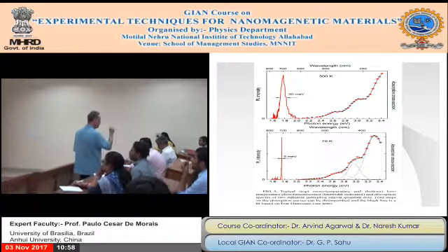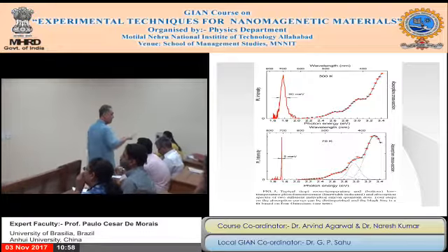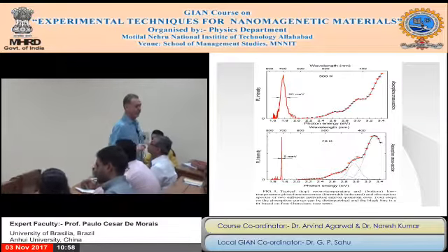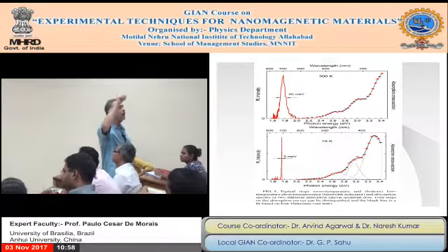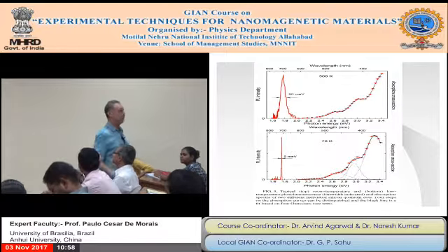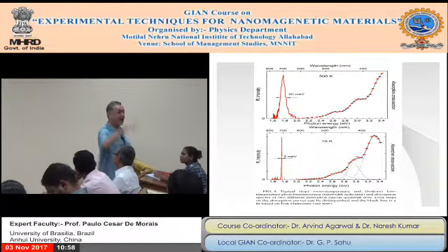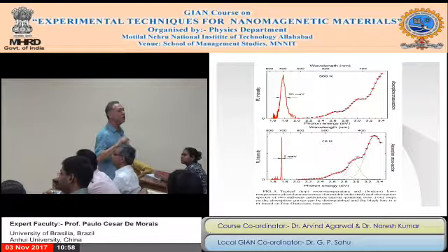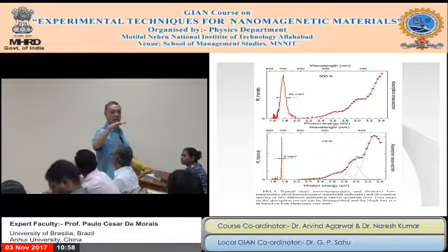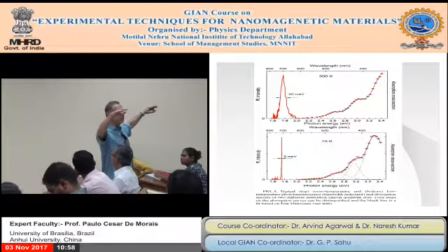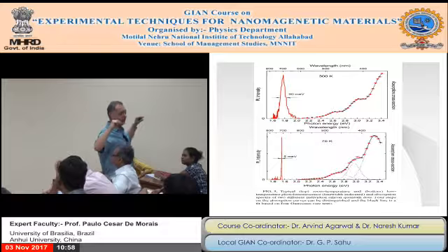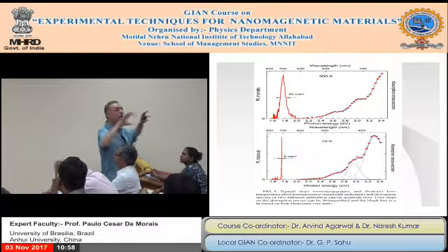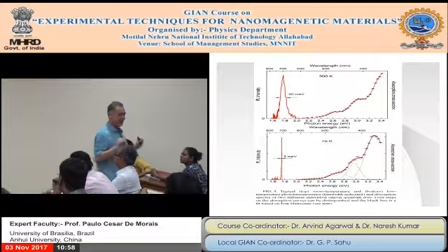The best way is to take your sample and put it inside a cryostat with liquid helium. Pump your liquid helium, which is at 4.2 K, with a mechanical pump, a big one. And then you lower the temperature down to 2 K, and the liquid helium comes to a phase transition to a superfluid state, and then it's very quiet. You can do optics, right?